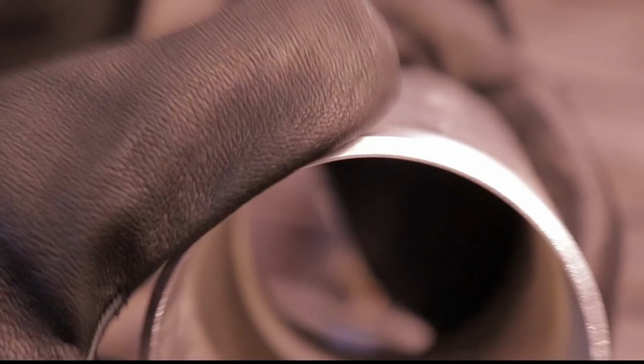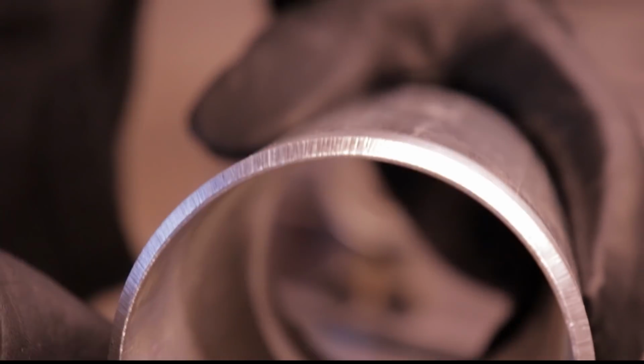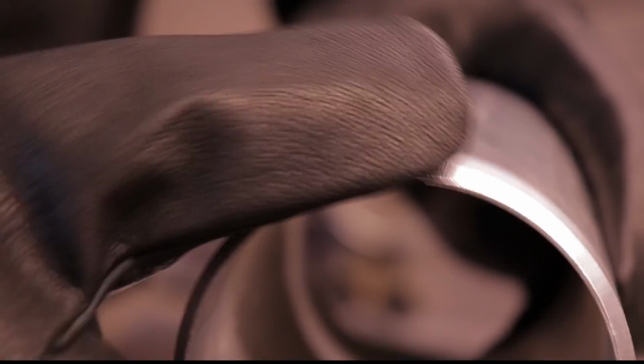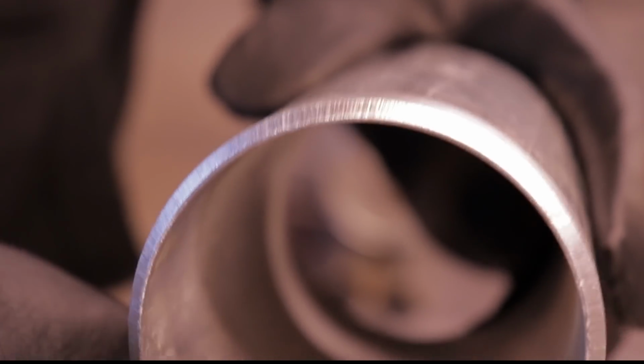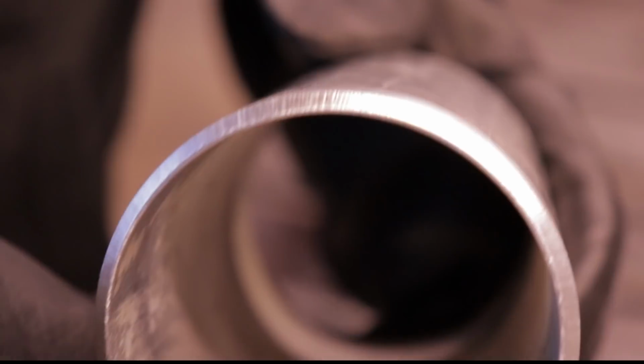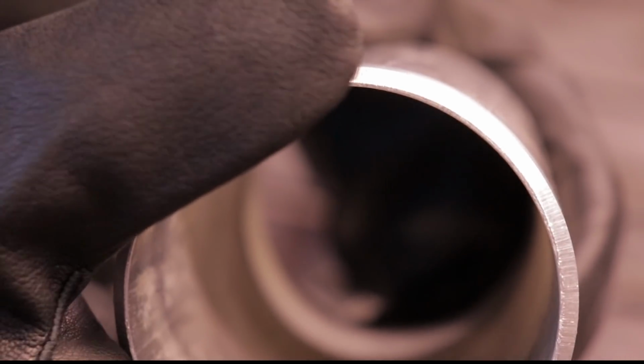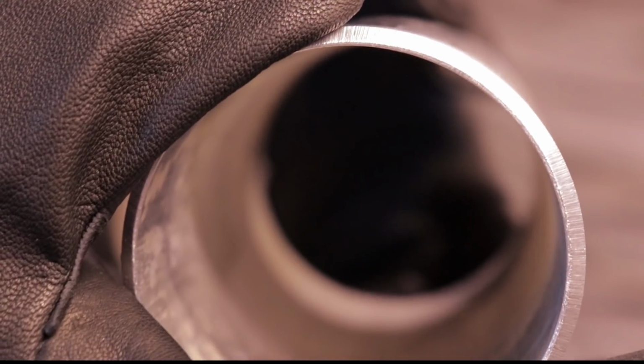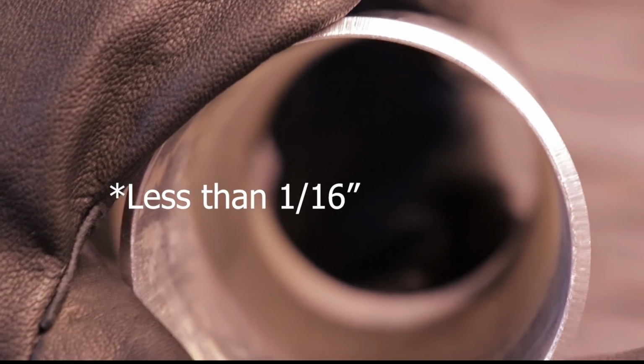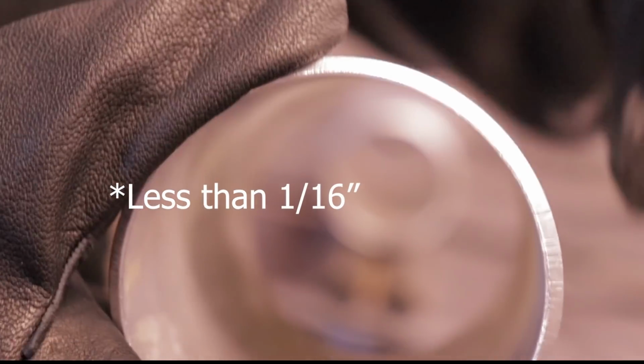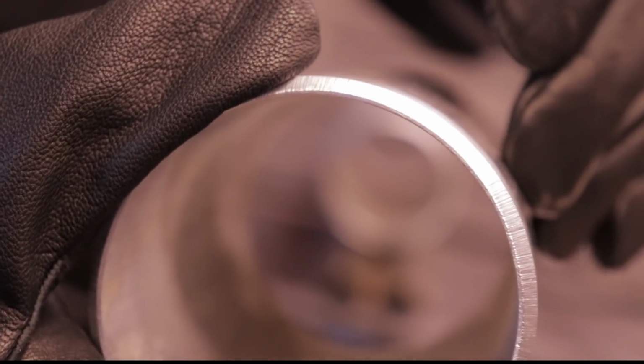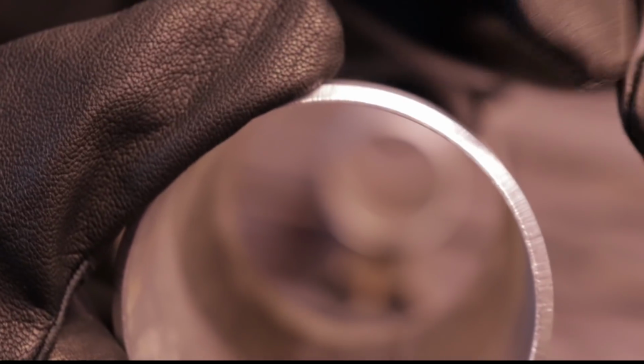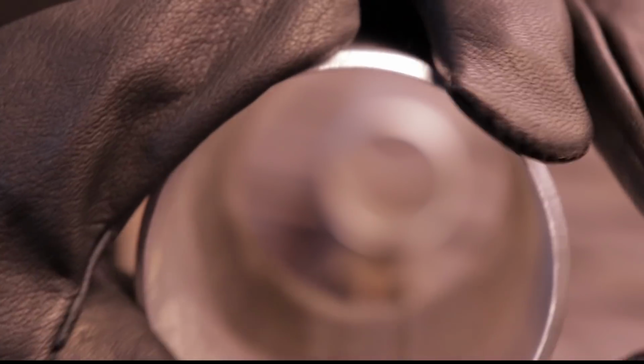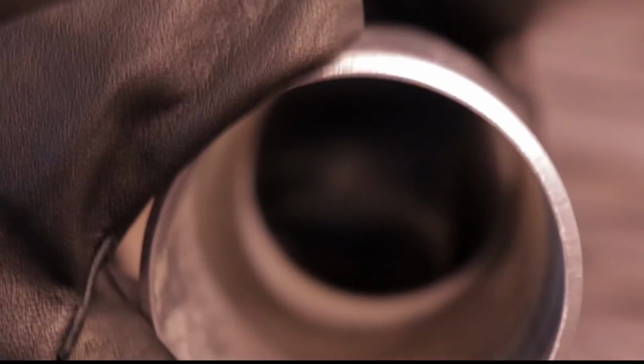So this is how I prep. This is what we call 3-inch thin wall tubing. It's basically 3-inch outside diameter tubing with 1/8-inch wall thickness. I like to grind a 45-degree bevel until there's just barely a landing on there, maybe just under a 1/16. I like it thin like that because then you don't have to use as much heat to penetrate in. So overall, the weld's going to be stronger, the material isn't going to heat up as much, and you get good penetration and still get good bonding, and you can do it in one pass on something this small.